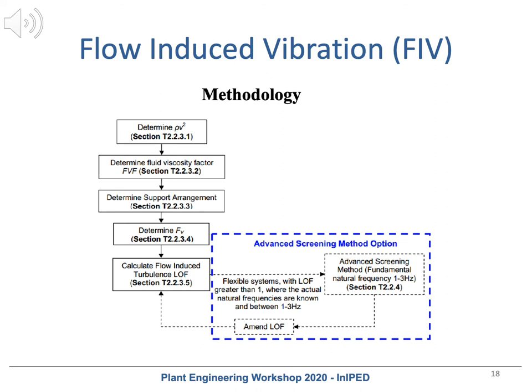First stage: a preliminary screening conducted to highlight lines of concern in accordance with the Energy Institute guideline, assuming worst case conditions. It checks that the kinetic energy should be less than 5,000 kg per meter per square second, according to the technical module of the Energy Institute guidelines. For those lines that don't comply with this requirement, a second stage is required.